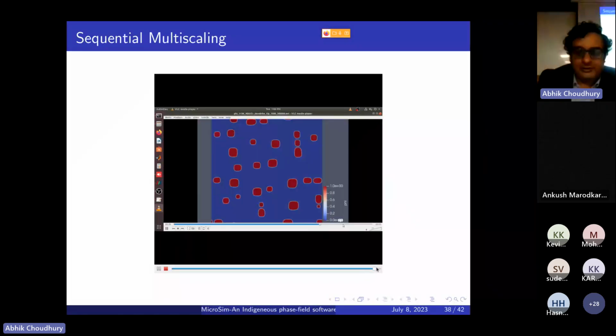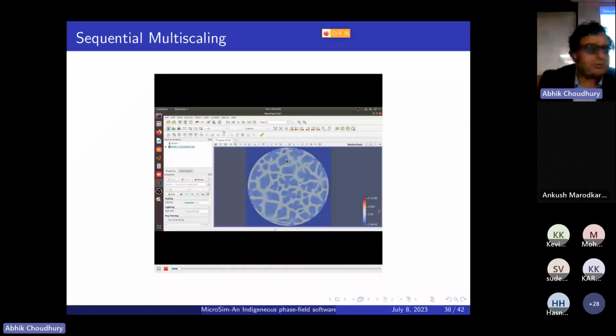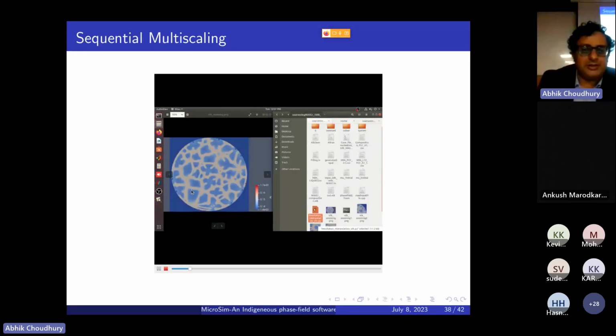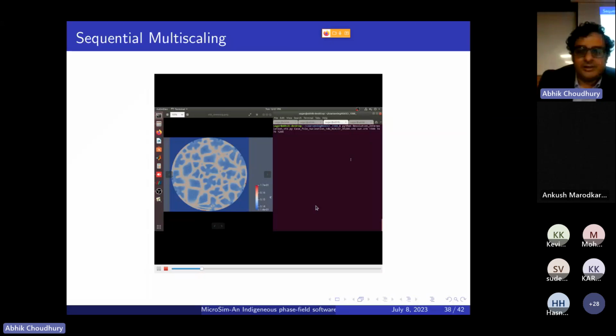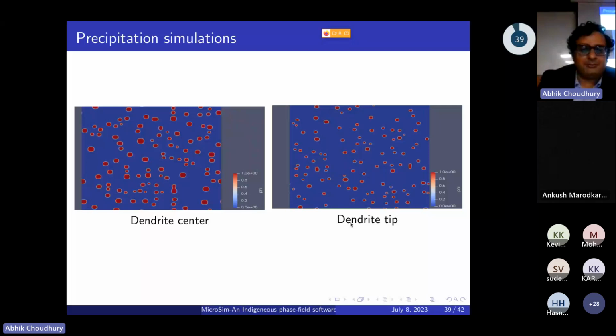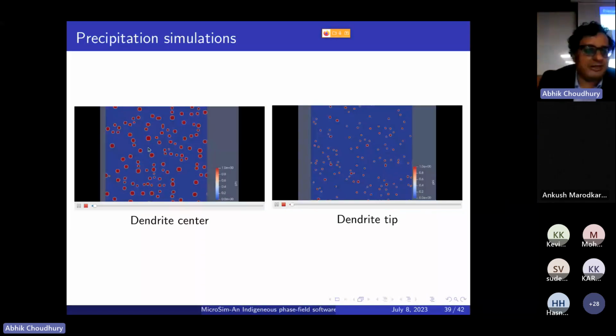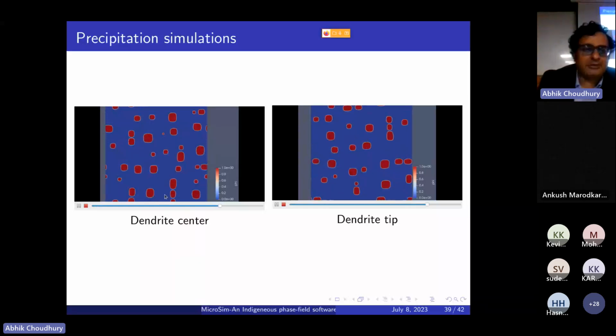So, for example, this is a precipitate simulation in the domain that you extracted, using the thermodynamic information that you extracted. Now, why is it important? Because you see there is a non-uniformity of composition in this microstructure. So the precipitate evolution that happens at the center core of the dendrite and at the tip of the dendrite will typically be different. You would like to map that particular difference in your microstructures, and that's where this particular tool becomes important. So this is, for example, a microstructure evolution of the precipitation reaction at the dendrite center, and the same is happening at the dendrite tip. There are observable differences which are not picked up visually, but this is much coarser than this, which is much finer.